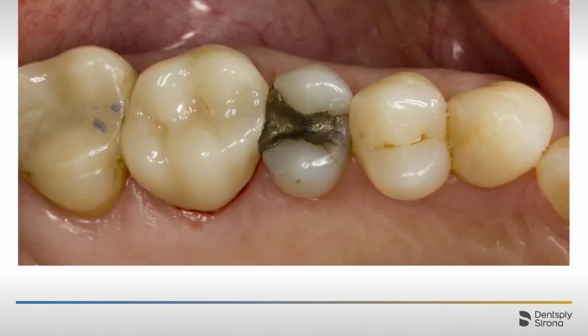So if you go ahead and you look at this zirconia restoration on tooth number 14, you can see this is the day I inserted it, so there's a little bit of tissue inflammation. But if you look at this translucent Katana STML zirconia, it's looking a little bit closer to glass ceramics. So it's giving us a higher strength, somewhere in the neighborhood of 750 megapascals of flexural strength, zirconia that actually looks pretty good. We can sinter pretty fast, and it's a chairside procedure. So we're going to start to see more and more of this, different manufacturers making translucent ceramics that can be manufactured much quicker. So this happens to be the Noritake Katana STML restoration.